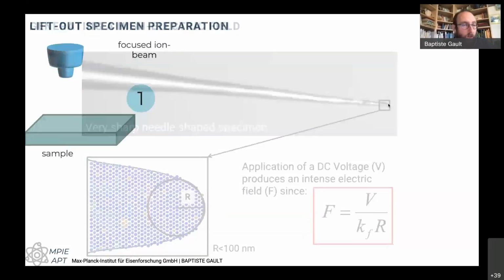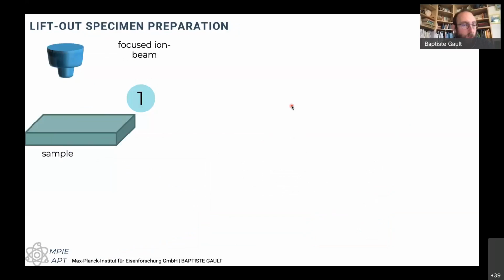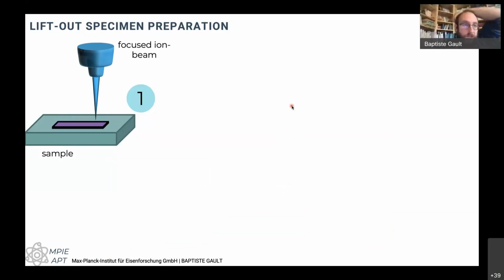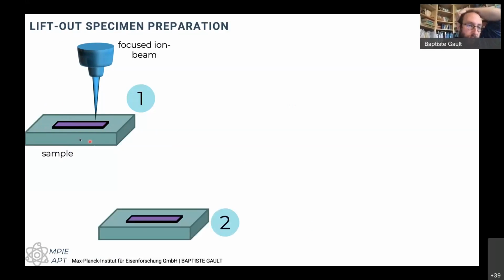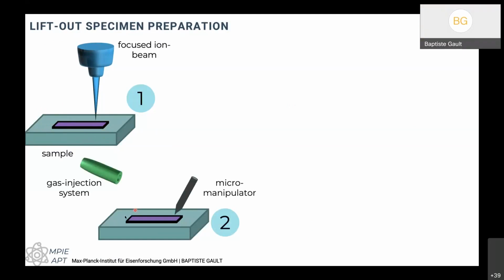So how do we make sharp needles? We can do this by electrochemical polishing, like the specimen that you've seen before. Increasingly, we do this using a focused ion beam. It's like an SEM, but on top of the electron beam, we have a secondary beam that is typically either gallium ions or xenon ions. So we can use it to sputter the surface very locally and dig trenches. We can start digging a first trench, a second trench, then come in with the micromanipulator, all of this inside the FIB. And then with the gas injection system inside the FIB, we can weld the micromanipulator to this little bar of the material that we are interested in, and then lift it out.